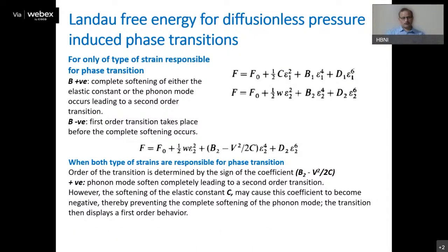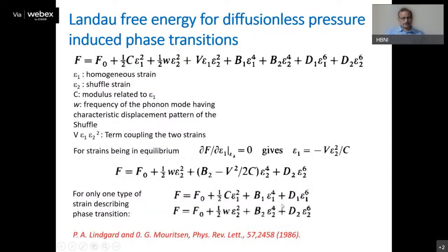Okay, one thing I did not tell: this C constant actually corresponds to the modulus of this homogeneous strain, so somewhat related to the elastic constants. And this omega actually corresponds to the shuffle strength. So this basically corresponds to the frequency of the phonon mode describing this shuffle.